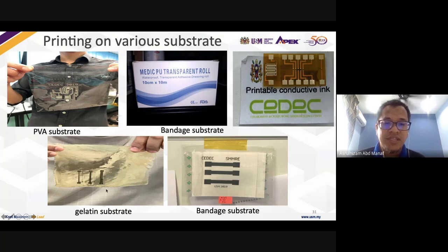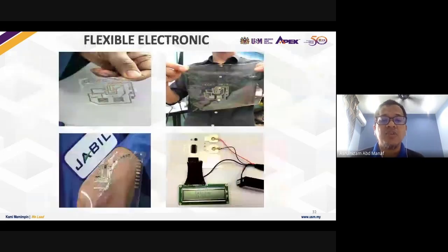This is on the gelatin. So the Band-Aid we bought from the pharmacy, we made it pure transparent. But we still struggle to get a good, very thin film of the substrate. So that is the PVA. And that's on the TPU, the thermoplastic polyurethane.